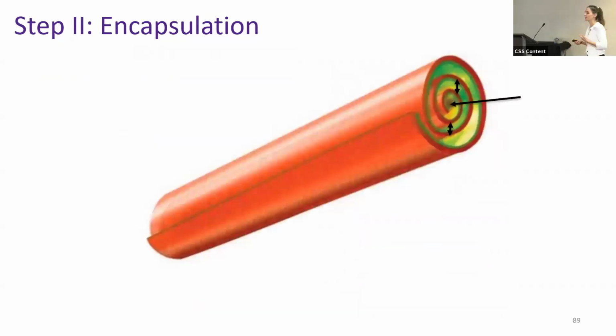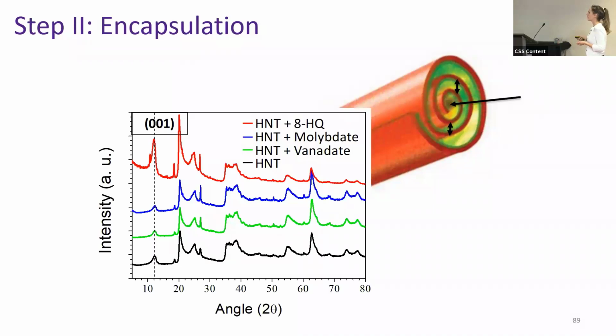And where exactly are these inhibitors within my nanotube? There are 2 different possibilities. They can either be inside this inner lumen or intercalated within these 2 layers of aluminosilicates. So we characterized them by XRD, and this peak here, the 001, corresponds to this interplanar distance.